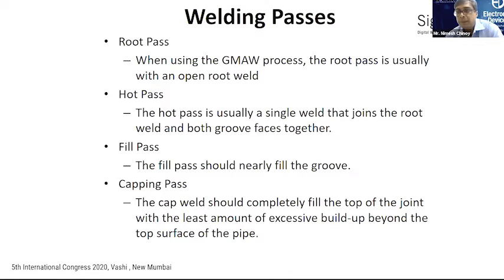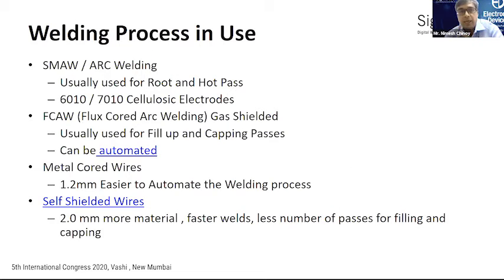The kinds of welding passes you do in a joint are a root pass, a hot pass, a fill pass, and a capping pass. Root pass is nothing but the first layer that you weld, and the hot pass is the immediate first pass after the root weld. Subsequently, you are just filling up material, which is called a fill pass, and when you want to finish the joint, you have a capping pass to give you an aesthetically beautiful look. Typically you use arc welding or MIG welding for the root and hot pass. Subsequently, you use flux core wires for fill-up and capping, wires which, as sir was sharing, will give you better productivity and faster use.